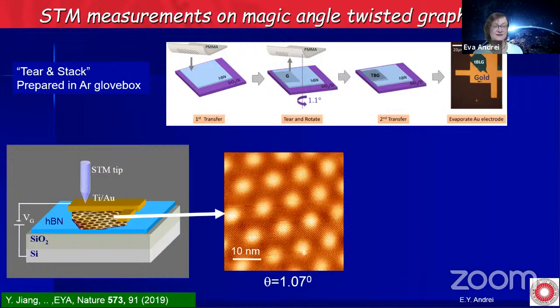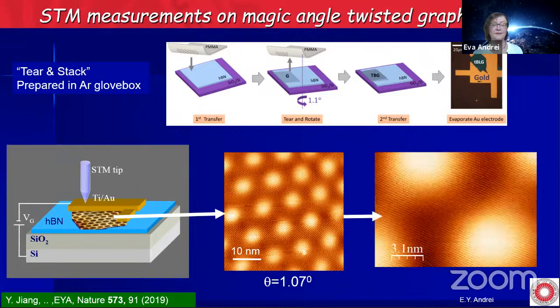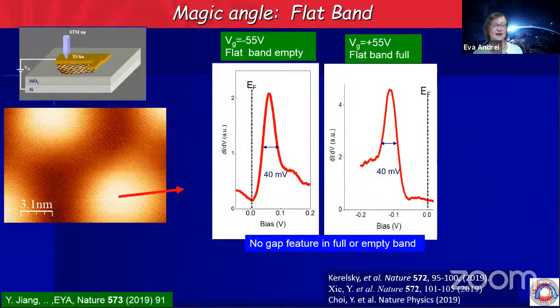This was a sample that was 1 degree. This is magic angle. And you see this beautiful Moiré pattern here. These are the AA regions surrounded by the AB regions. And zooming in, you can see the atoms. You can see that they're right on top of each other in the AA regions and form AB stacking, or Bernal stacking, in the AB regions.